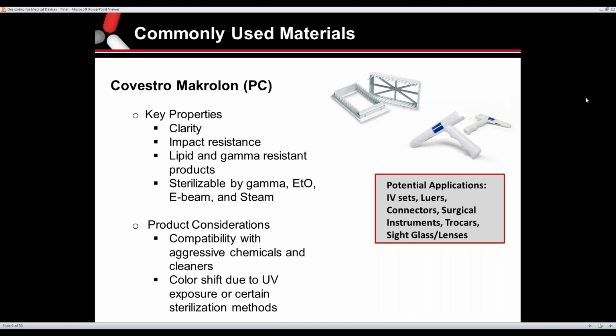Another consideration is that polycarbonate resins, the color can shift due to exposure to UV light and gamma sterilization. And Covestro actually does have a color adjusted material for use with gamma, so that taking into account the color shift that can take place during gamma, they do a color correction, but it's just something to consider.